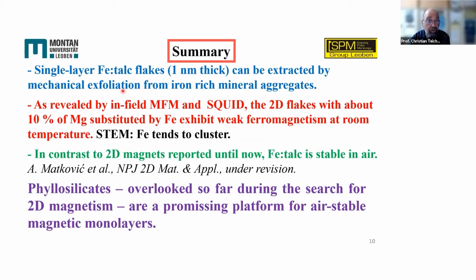Yeah, with that, I would like to summarize. We have single layer iron talc flakes, 1 nanometer thick, that can be extracted by mechanical exfoliation from iron-rich phyllosilicates, in this case iron talc. And as revealed by in-field MFM and SQUID, the two-dimensional flakes with about 10% of magnesium substituted by iron exhibit weak ferromagnetism at room temperature. We also did scanning transmission electron microscopy that shows that the iron tends to cluster into clusters a few nanometers large. In contrast to 2D magnets reported until now, these iron talc layers are really stable in air, and we suggest that phyllosilicates, overlooked so far during the search for 2D magnetism, are a promising platform for air-stable magnetic monolayers.